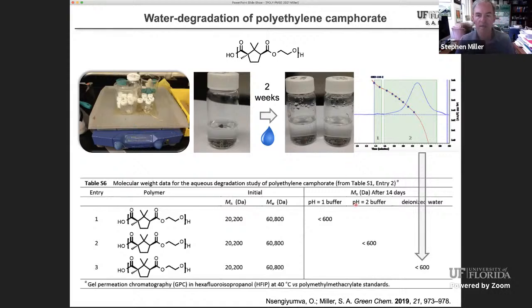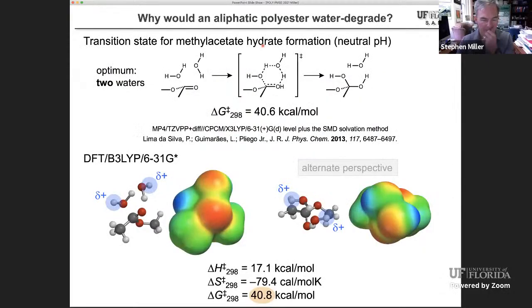And when we look at that little glob by GPC, we have a polymer that's lower than our lowest PMMA standard. And so it seems to have completely depolymerized just in neutral conditions in deionized water, which is kind of unusual for a polyester, right? Again, polylactic acid does not do that. So we wanted to figure out maybe why this is happening and what makes this possible for an ester.